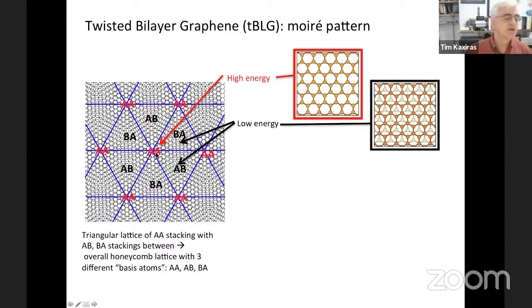So this is what you see when you create a twisted bilayer graphene. So you see two layers now on top of each other, and there are regions labeled AA, where the two layers are exactly on top of each other. So you only see one set of atoms or one honeycomb lattice. There are other regions where the two layers are offset. So you see all the atoms on the top layer and half of the atoms on the bottom layer. So that's the standard stacking of layers, of two successive layers in graphite.